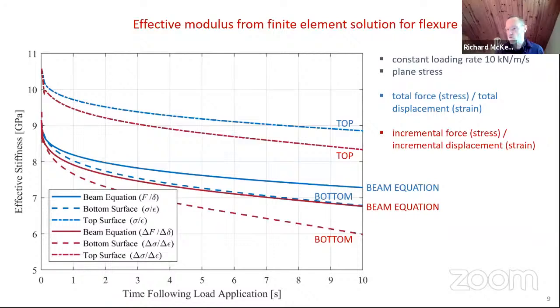The reason for that is because there's more displacement as a result of viscoelasticity in the previous plot I showed, because the load is on for the entire 10 seconds. Here we're ramping up the load, so effectively we've had less load on the beam over that 10 seconds. I've also plotted incrementally from the beam equation a delta F and delta displacement, and also the delta stress and delta strain, so the incremental values of stress and strain. You can see that in that case, it's actually less. So you have a slightly lower effective modulus when considering incremental values, and that's basically because you're starting from a lower point.